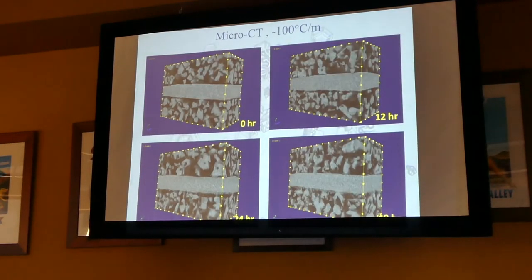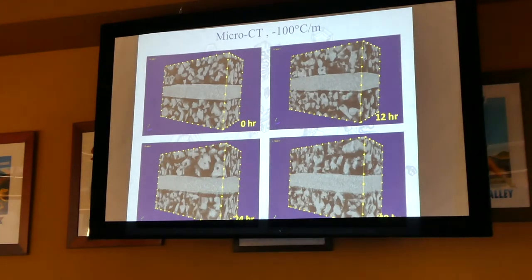So from the micro CT work, we did a time-lapse micro CT. Micro CT is a CAT scanner for small things. We have it in our cold lab at Dartmouth, but also at MSU. We have all the same stuff. And what we saw was we started off with a nice smooth ice lens, and we got this crystal growth that occurred from the bottom side of it while all the grains around were becoming faceted. This was actually seen first in the literature by Ethan Green during his dissertation. He saw something similar with his experiments. So we saw that again.